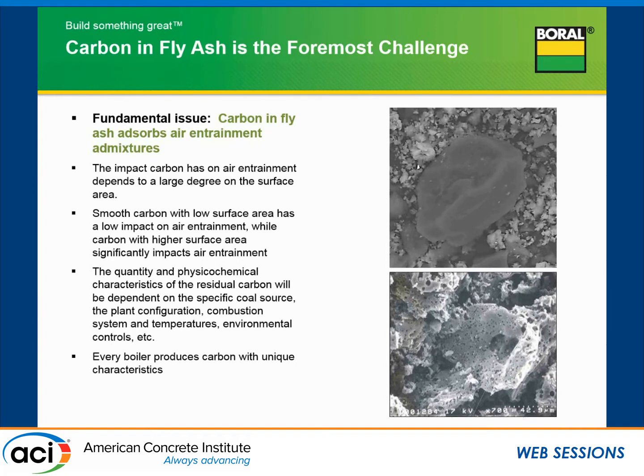Carbon takes on many different types, and I'll show you some slides to illustrate that. In these pictures, this is a piece of carbon out of one of our sources. You can see it's very glass-like, very hard, with very little surface area. So it will have little to no effect on air-entraining admixtures. By comparison, this piece of carbon has many, many pores — very many micropores — giving it a much higher specific surface area. So even if they represent the same quantity, they'll have drastically different influences on how they react in concrete.